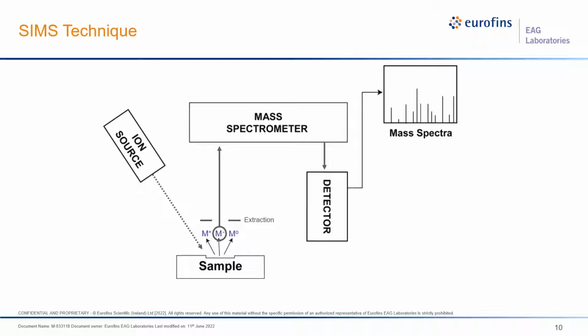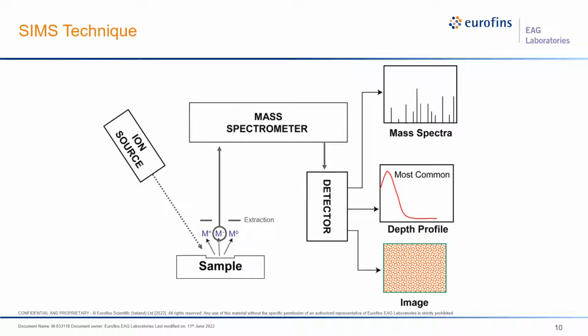This slide shows in block form what makes up a secondary ion mass spectrometer. We have an ion source shown on the left, and in that source we produce ions of either oxygen or cesium, and these ions impact the sample and sputter the sample. The material sputtered from the sample is mainly neutral, uncharged, and we cannot use that material. We can only use the material that is sputtered from the sample as positive or negative ions, and probably 99.99% of the material sputtered is neutral and unusable. So the positive or negative ions are extracted and focused into the mass spectrometer.